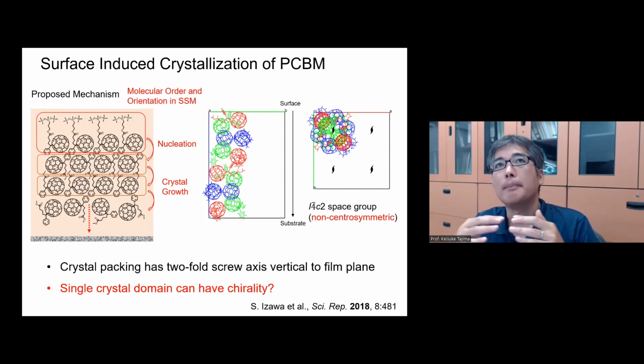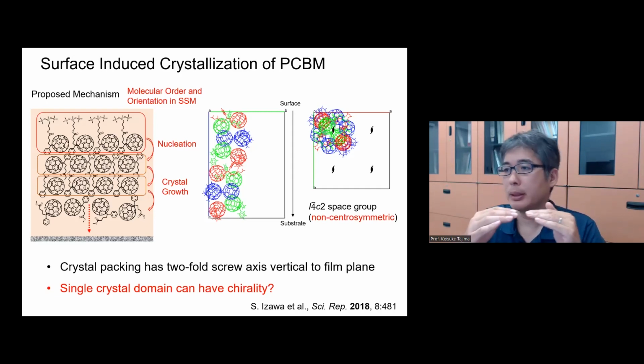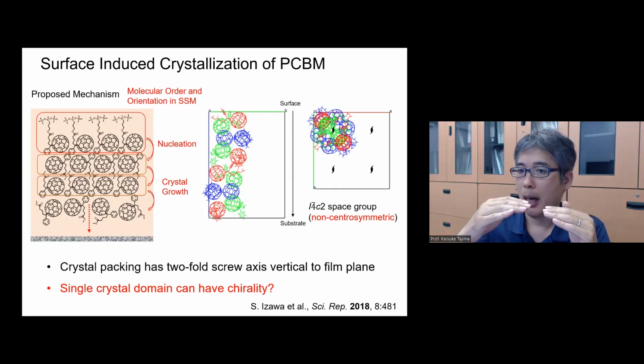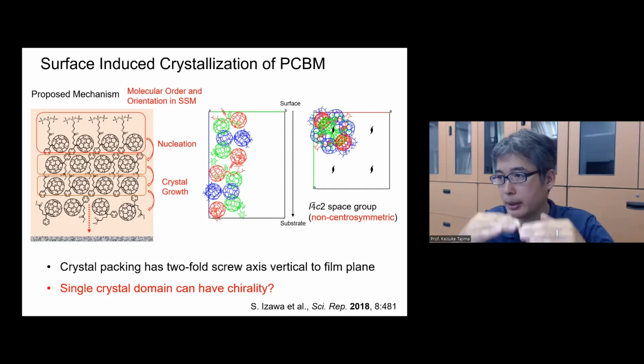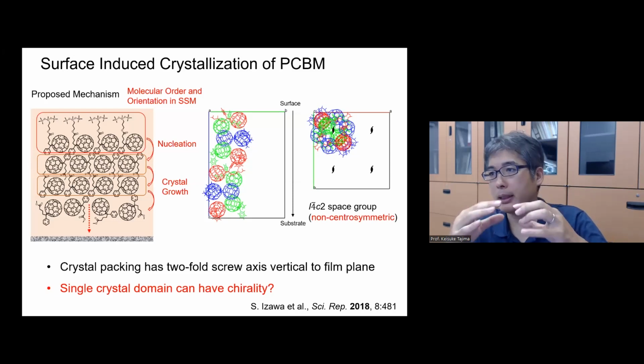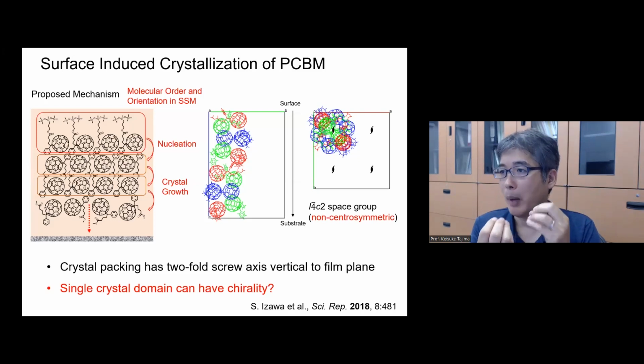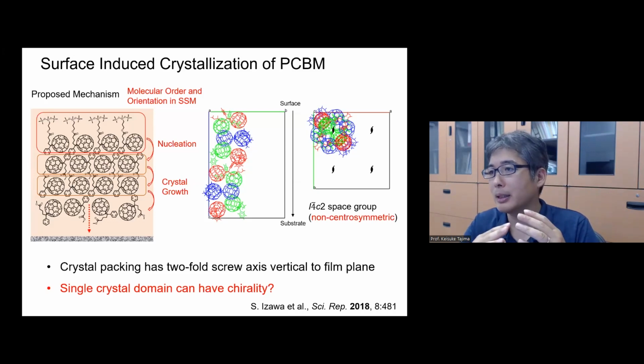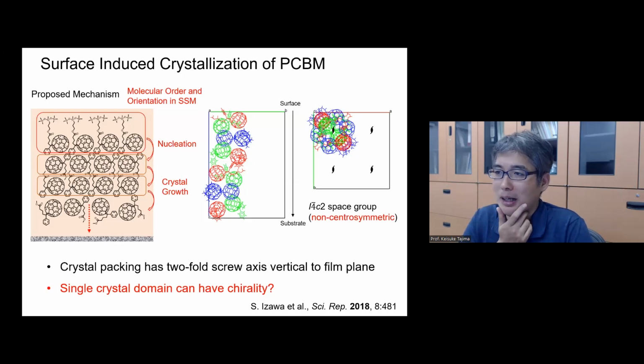But it needs to be amorphous first before the thermal annealing, and then after thermal annealing it crystallizes and becomes highly crystalline. Then probably that's the best case. But if the crystallinity is too high, then it already crystallized inside the film after the deposition, and thermal annealing doesn't affect it so much. So in that case, orientation control could be difficult. I'm talking about it very simply, but it's a really complicated play between the surface energy, the crystallinity of the material, and the interaction between the surface molecules and the molecules in the bulk. So it's highly dependent on the system, unfortunately. It's hard to answer in general.